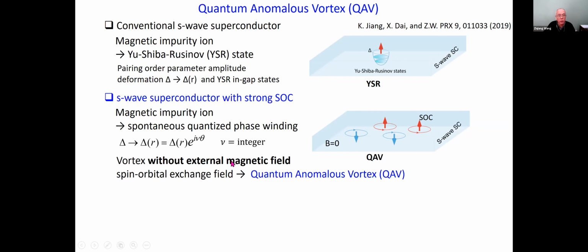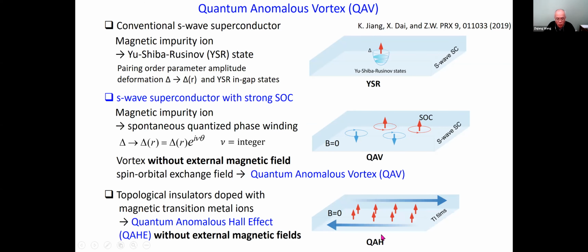And the role of the magnetic field is played by the spin orbital exchange field. And we call such vortices quantum anomalous vortex. And it is, formally speaking, a superconducting analog of the quantum anomalous Hall effect, in which you take a topological insulator thin film and dope with magnetic ions and produce a quantum anomalous Hall state without external magnetic field. So the quantum anomalous vortex per se has nothing to do with Majorana zero mode. However, it came to light because of the search for Majorana zero modes in iron-based superconductors.